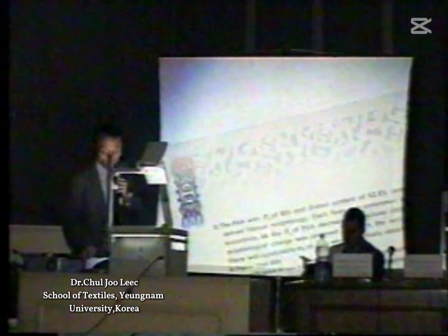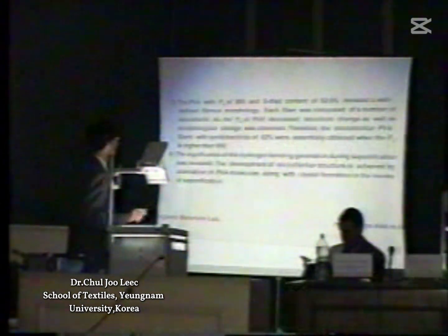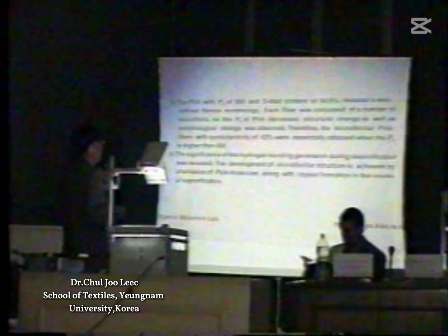This is the final slide. The polyvinyl alcohol with degree of polymerization over 800 and syndiotactic diad content over 62.5% revealed a well-defined fibrous morphology. Each fiber is composed of a number of microfibrils. As the degree of polymerization of PVA decreased, structural changes as well as morphological changes were observed. Therefore, microfibrillar polyvinyl alcohol fibers with syndiotacticity of 62% were essentially obtained when the degree of polymerization is higher than 800. Thank you for listening.